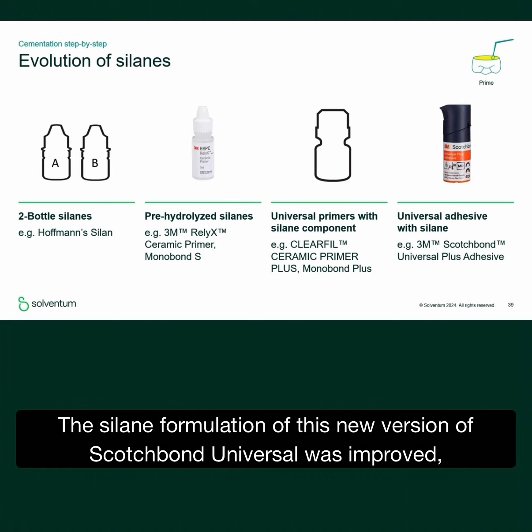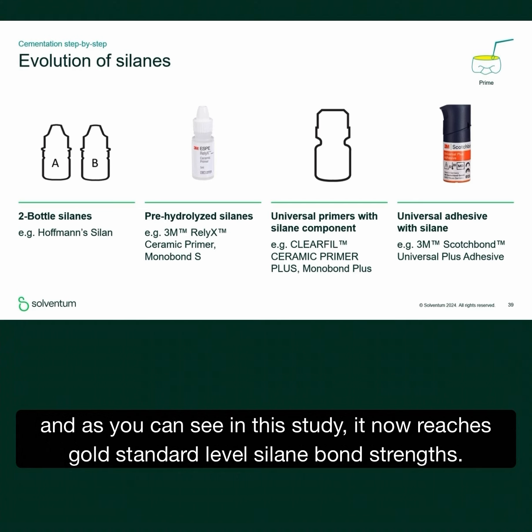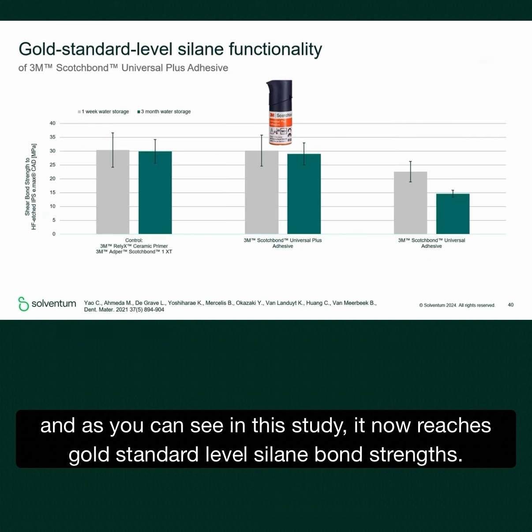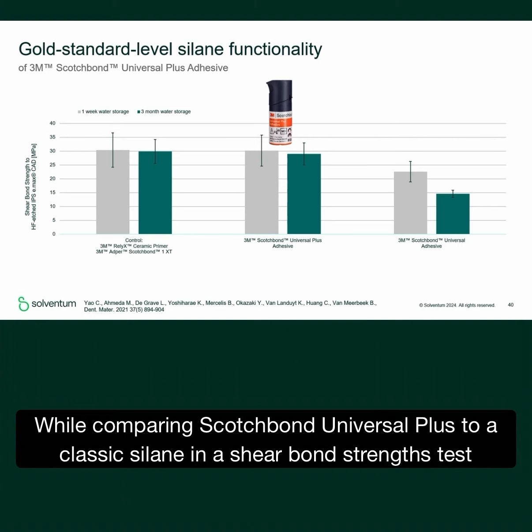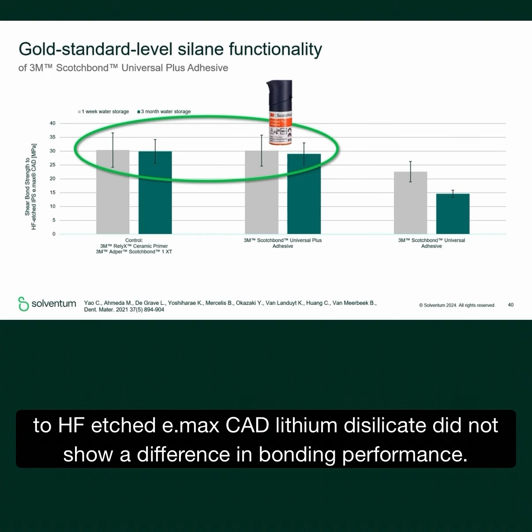The silane formulation of this new version of Scotch-Bond Universal was improved, and as you can see in this study, it now reaches gold standard level silane bond strength. So comparing Scotch-Bond Universal Plus to a classic silane in a shear bond strength test to HF etched Emax CAD lithium disilicate did not show a difference in bonding performance.